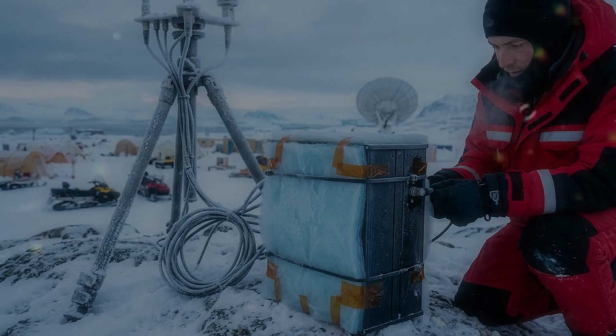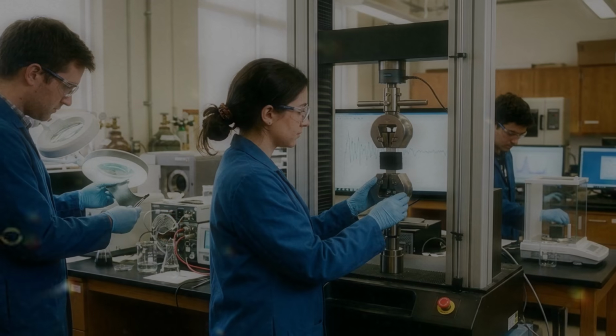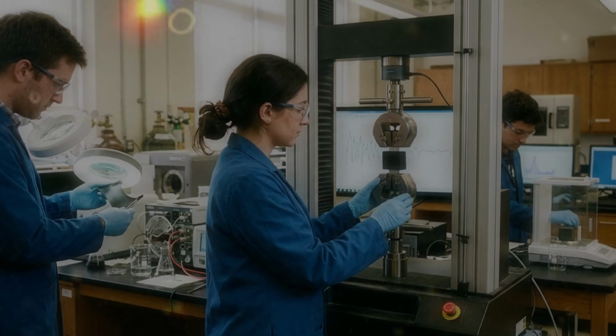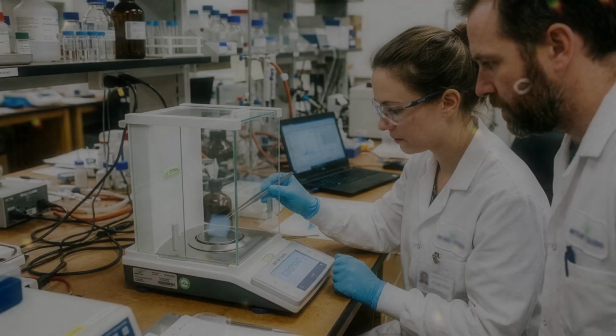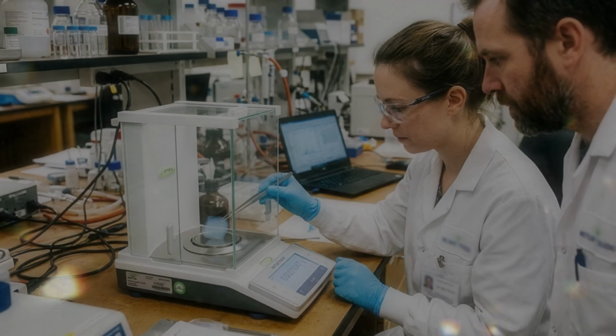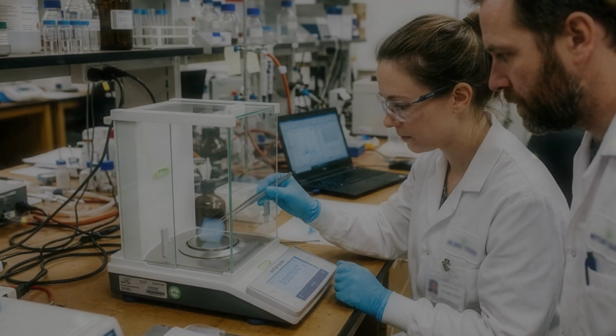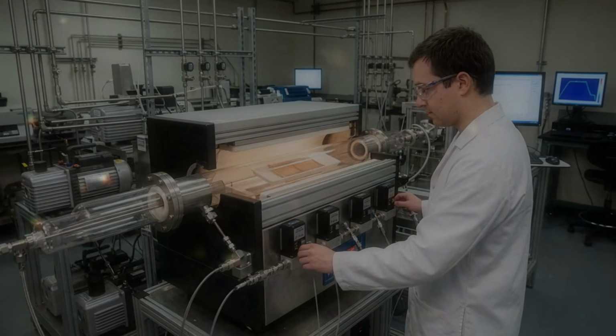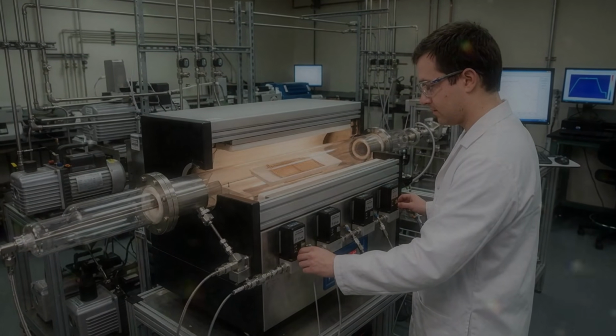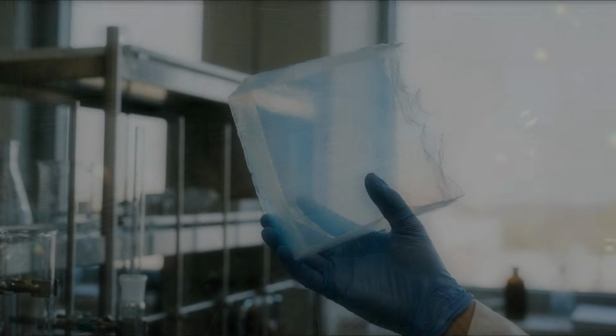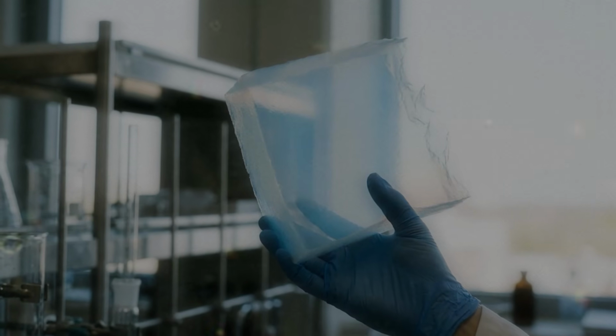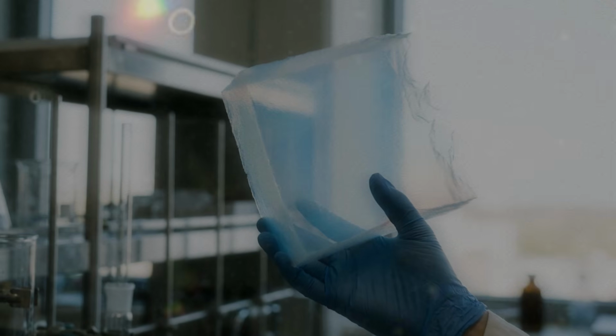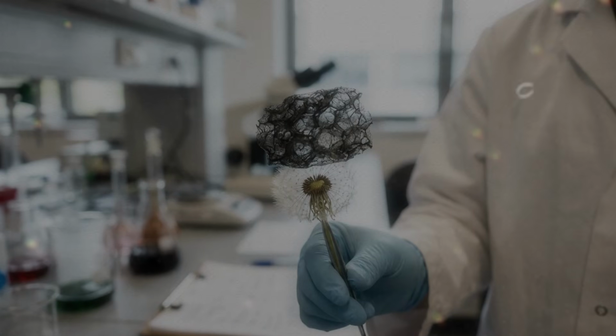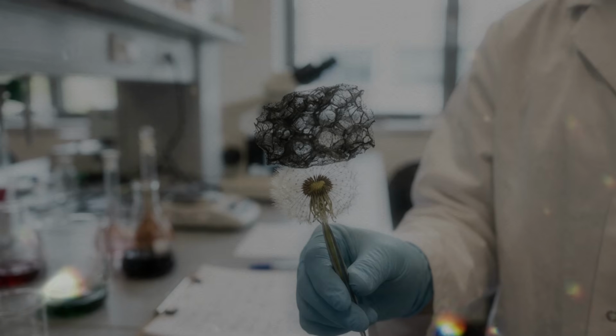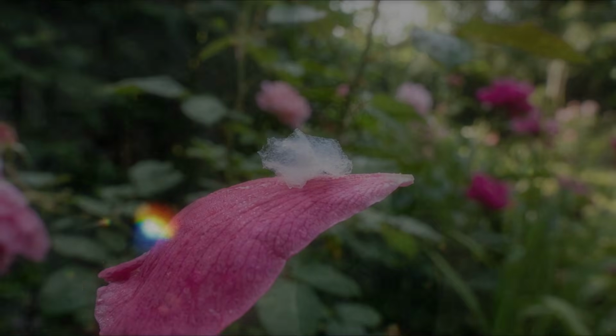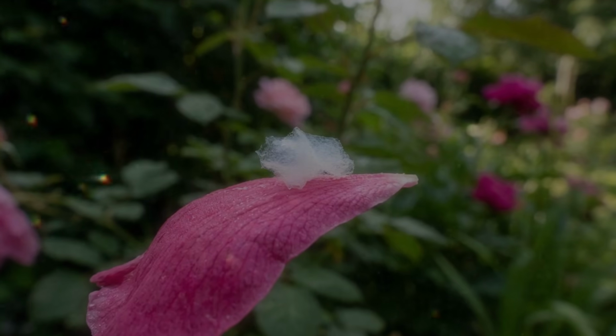The pores also explain why many aerogels slow the movement of heat. Heat can travel through a solid framework, through gas, and through radiation. Aerogel interferes with all of these routes in different ways. The solid framework is thin, so there is relatively little material available to carry heat directly from one side to the other. The gas sits inside extremely small pores, which limits the way its molecules move and collide. Convection, the circulating motion that transports heat through larger pockets of gas, is greatly restricted because there is not enough room for the gas to form useful currents. Certain aerogels also scatter or absorb some thermal radiation. This combination can make aerogel an excellent insulator.